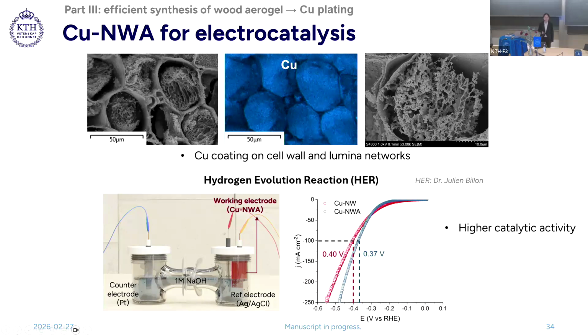From linear sweep voltammetry, we can see copper-plated aerogel has better catalytic activity compared to the reference, requiring lower overpotential to reach the same current density. This favorable electrochemical performance of copper-plated aerogel is attributed to the copper-coated network and its mesoporous structure, which provides more accessible active sites and favorable mass transfer.